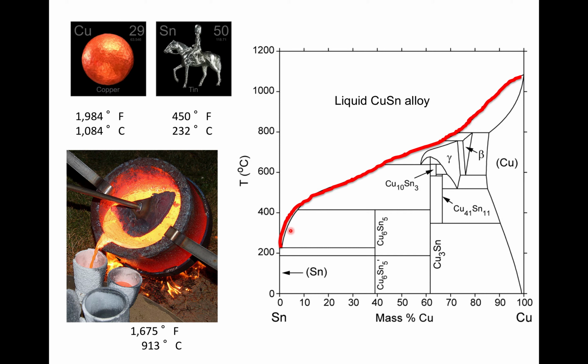And the red line shows you that as more tin is added to the tin-copper mixture, the melting temperature changes. So if we start with pure copper here that melts at a high temperature, as we add more tin, watch my laser pointer, the melting temperature of the mixture decreases. So if we have a mixture of approximately 50% tin, 50% copper, it has a melting temperature over here of about 650 degrees, which is give or take half of the melting temperature of pure copper. So the more tin you add, the lower the melting temperature.